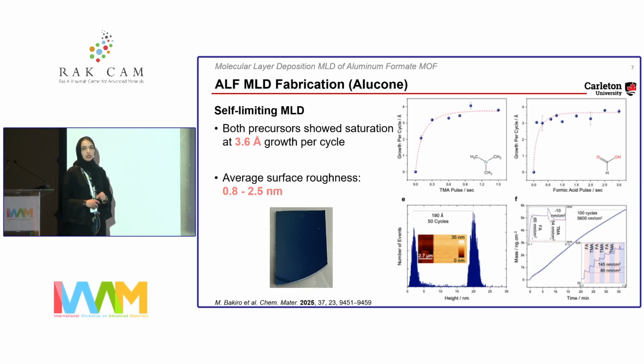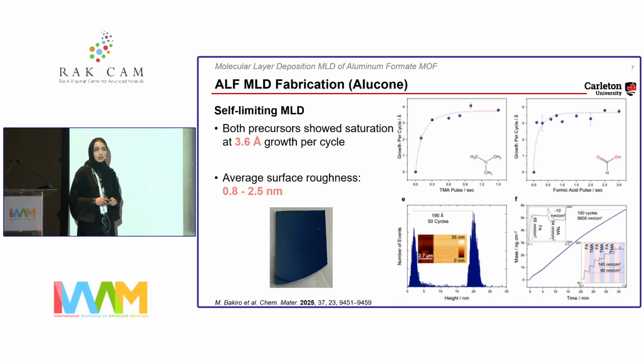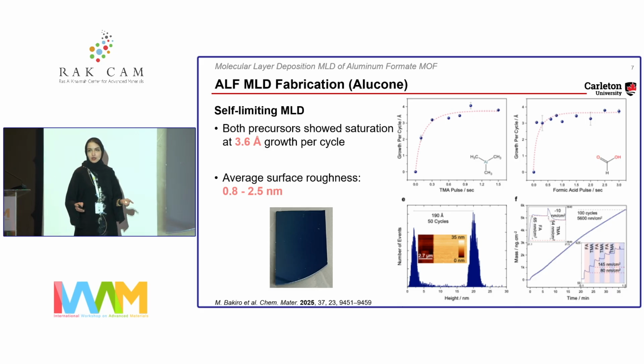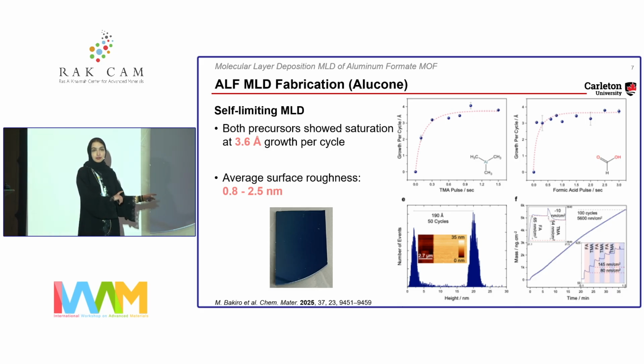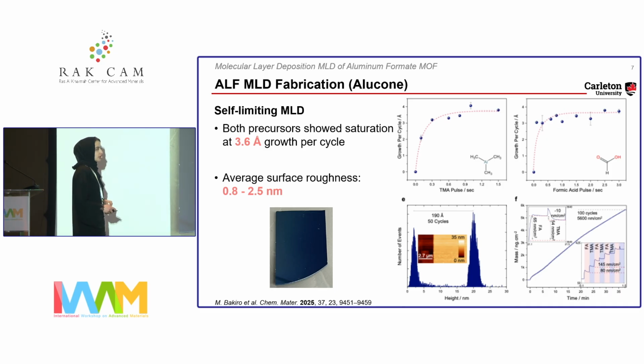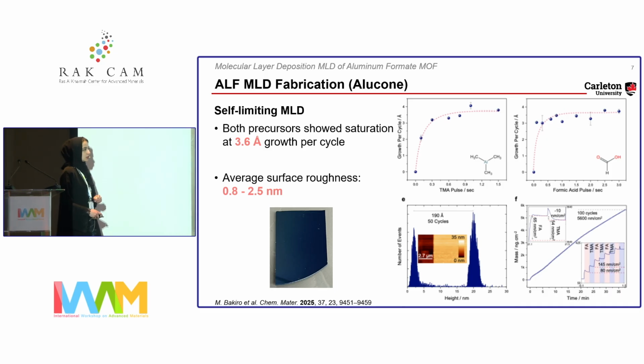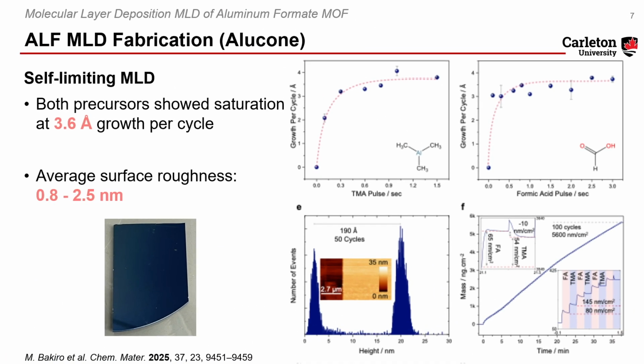We also monitored the growth by quartz crystal microbalance. It's a normal balance, like the one you use at home, except this one can measure atoms. So we throw one of these in the chamber, and we were looking at the growth. On the y-axis, you have the mass gain, and every time you pulse a material on the surface, you can see an increase in the mass on the balance. And then you want to see a stepwise growth, and that's how you know it's an MLD system.